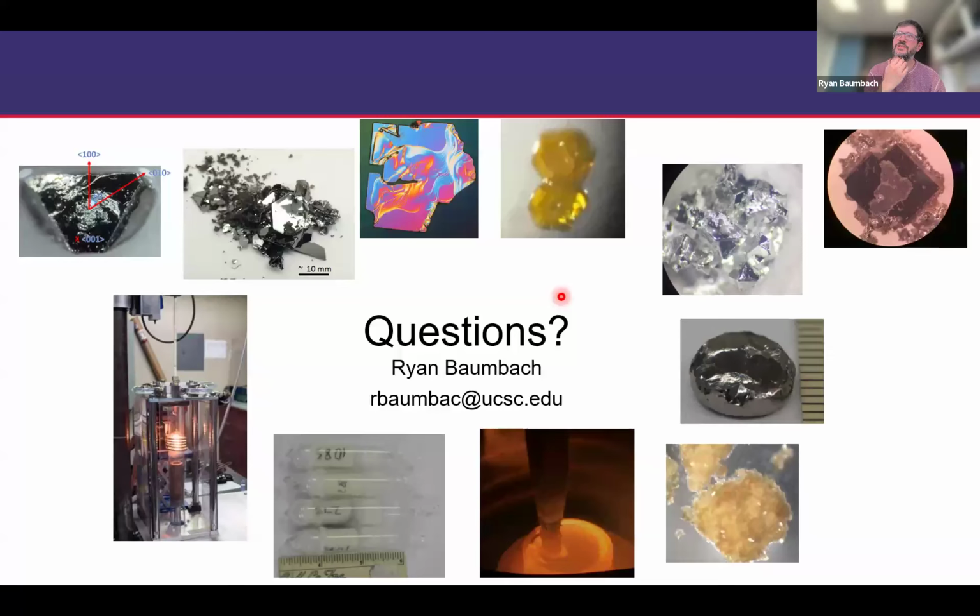I suppose a different consideration that might matter for some materials is if it did undergo some sort of structural phase transition. You know, steels do a martensitic phase transition, and it does matter exactly how you heat treat them. So if you were at a congruently melting phase and there was an additional structural phase transition below it within the solid, then the rate at which you cooled through it could matter a lot. But that would be some sort of special case. Does that get at the question?